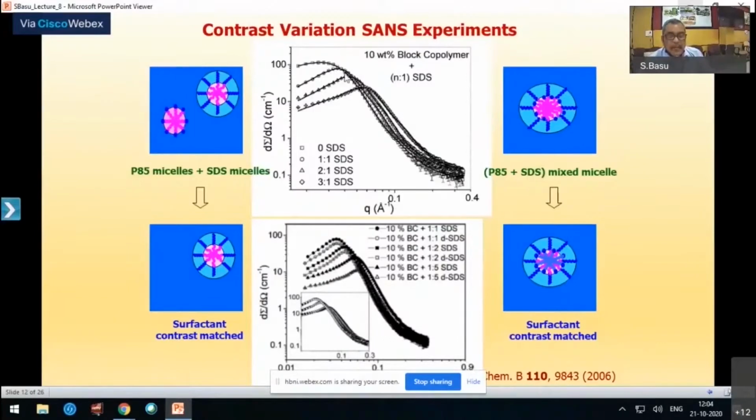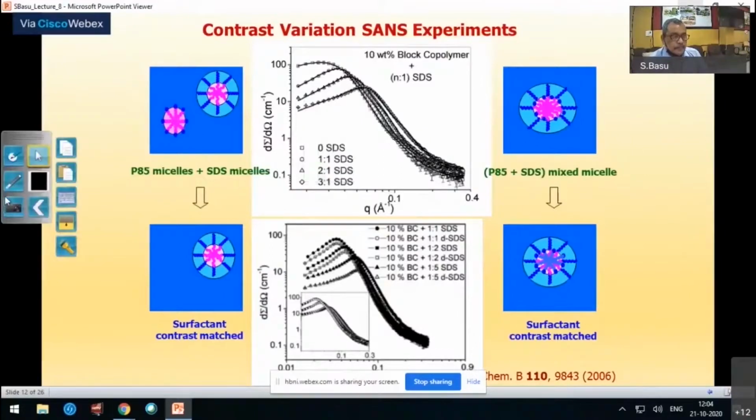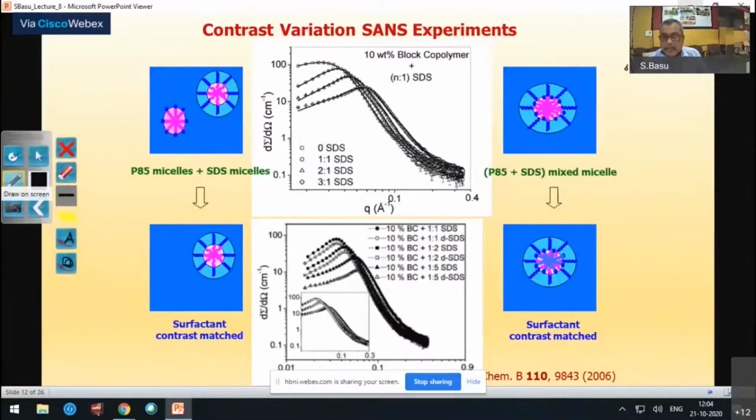This peak is actually a signature that even in liquid medium, these micelles which are moving around dynamically, they do have a local structure. So this local structure gives this peak, and this fall gives the form factor, and I can look at structures typically in the range of 10 angstrom to 100 angstrom. If I am able to push my Q range to lower and lower values, I can see the fall at lower ranges, and I can see larger and larger objects.